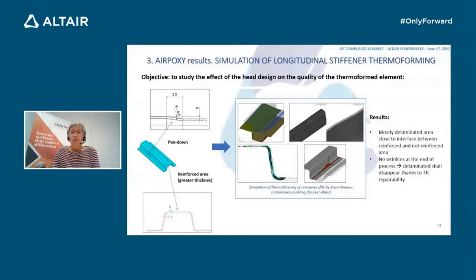The simulation tool was used to study the influence of the pen down and variable thickness on the quality of the thermoform longitudinal stiffener. It was observed that mostly the delaminated areas appear close to the interface between reinforced and not reinforced areas, but no wrinkles are expected at the end of the process, as the delamination shall disappear thanks to the repair capability of the 3R resin.